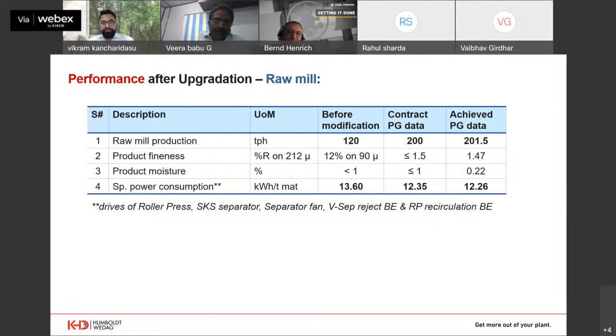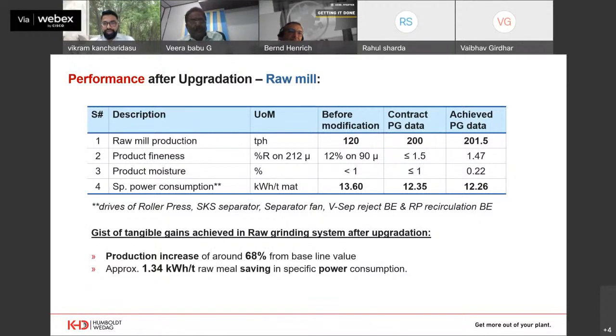Coming to the raw mill system, the contract guarantees are met easily. And if you compare the figures with the before modification, against 120 TPH, we have achieved 201.5 TPH. And in the power consumption also, in specific power consumption, 13.6 it was operating earlier. Now the plant is operating at 12.26 kilowatt hour per ton. So again, the takeaways in this raw grinding modification: production increased by approximately 68% and 1.34 kilowatt hour per ton of raw meal saving in specific power consumption.